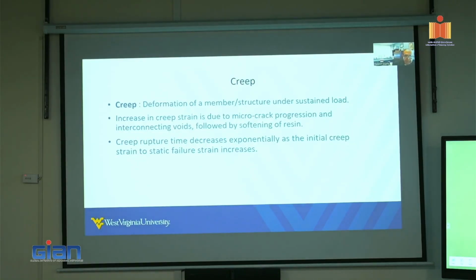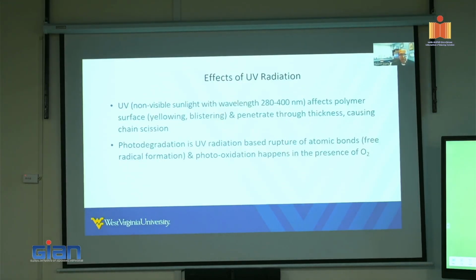There is strain that occurs, and this results in microcrack progression, interconnection, softening of the resin, and ultimately failure, which is a very undesirable event. If a composite is exposed to sunlight, a component of that is UV light. This can affect the polymer and result in discoloration, yellowing, and if the effect goes deeper, you can have chain scission and loss of properties.